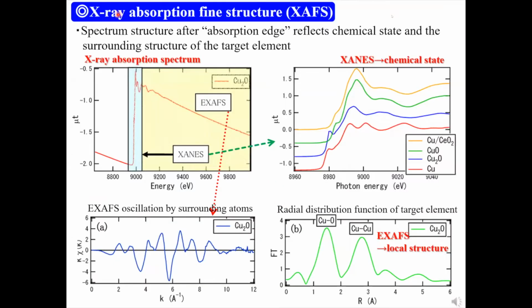XAFS is the abbreviation of X-ray absorption fine structure, a method of X-ray absorption spectroscopy. An X-ray absorption spectrum shows a sudden jump at a certain energy, called the absorption edge. The spectrum structure around the absorption edge reflects the chemical state and the surrounding atom coordination. The edge energy is element specific. Therefore, the information of the target element can be analyzed without interference of other elements.